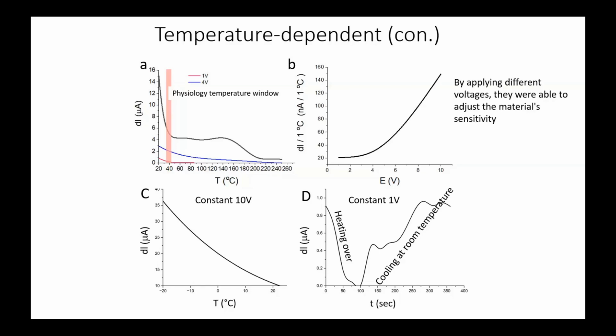I want to focus on this bar, which is the physiologic temperature window, and we can see that in this bar we have a very nice slope, and it is voltage dependent. We can moderate the sensitivity by applying the voltage. As we see in this plot, we can heat and then recover after cooling. Here we cool at room temperature, but we can cool in other ways.